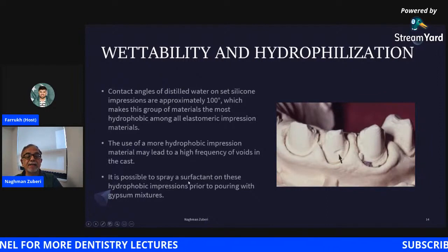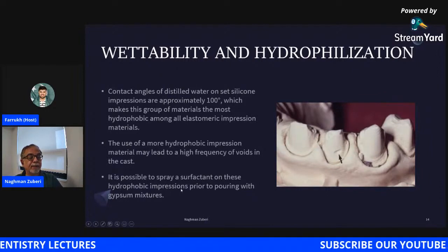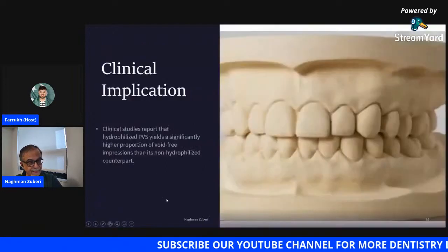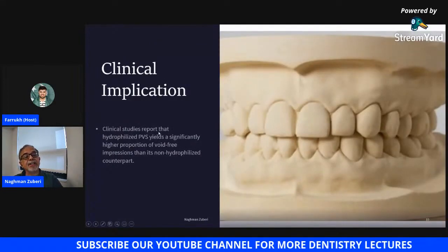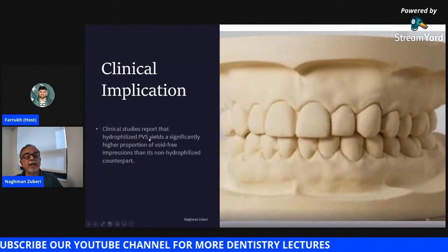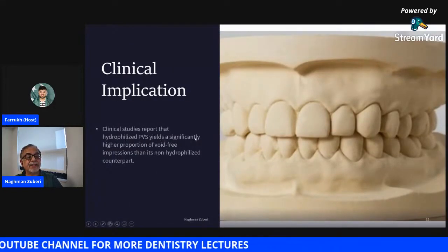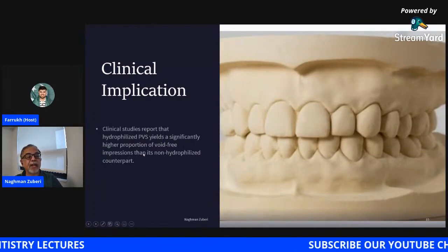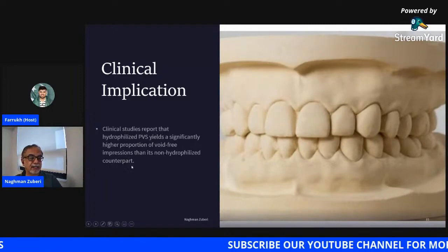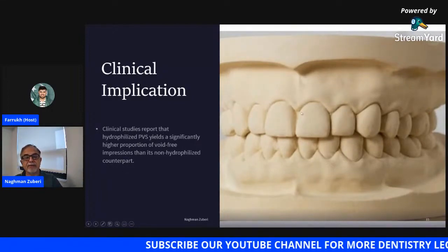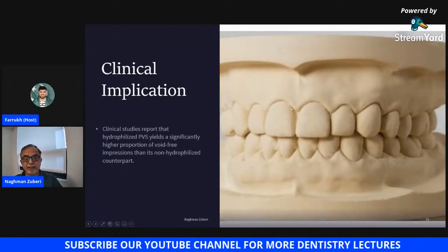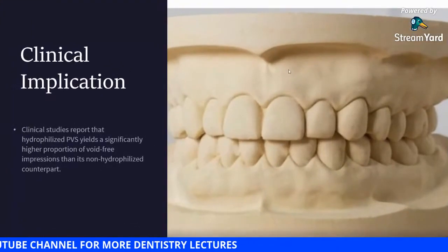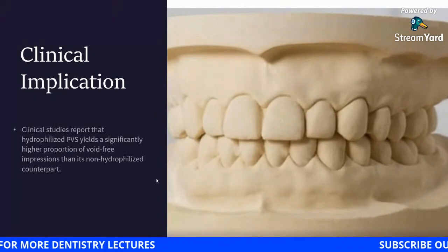It is possible to spray a surfactant on these hydrophobic impressions prior to pouring with gypsum mixtures. Clinical studies report that hydrophilized PVS yields a significantly higher proportion of void-free impressions than its non-hydrophilized counterpart. You will get very nice details without any voids, very smooth surface and very beautiful surface details.